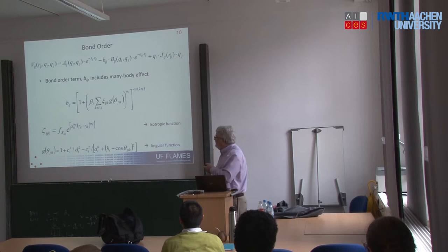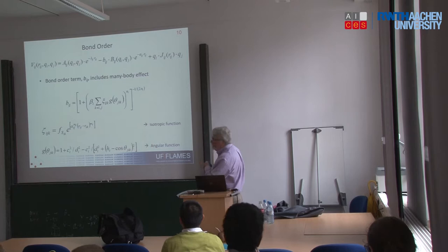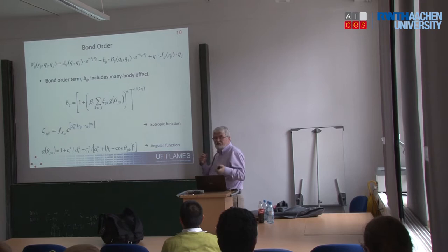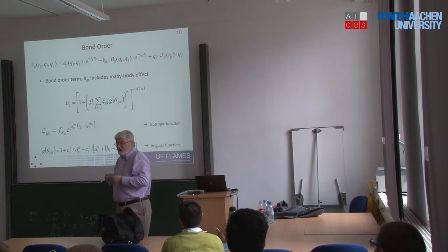Now, we're not going to walk through all these terms, but what you see is this is energy as a function of position. It is also a function of charge as well. So this says that my interactions between two atoms depend not only on their relative positions, they depend on their charges. So if we were to do an optimization process, we would not only optimize our positions, we would also optimize our charge.